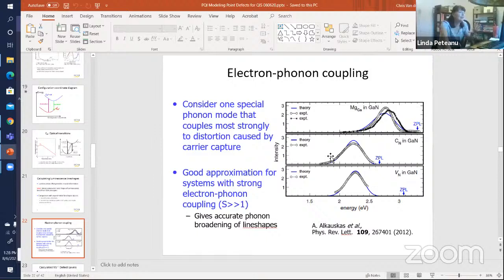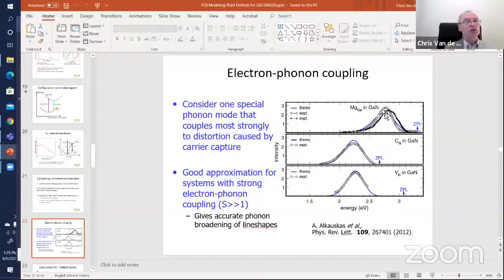So it seems like there's a pretty huge distortion of the lattice given the size of the Stokes shift that they're measuring. Is that right? That is right. For these examples of defects and impurities in gallium nitride, invariably we find very broad line shapes, large relaxation energies. For quantum emitters, such large relaxations are typically not desirable. You actually want a small Huang-Rhys factor. And I think for both the centers in hexagonal boron nitride I talked about, the Huang-Rhys factor is smaller than 2. So that's a good sign for those defects.